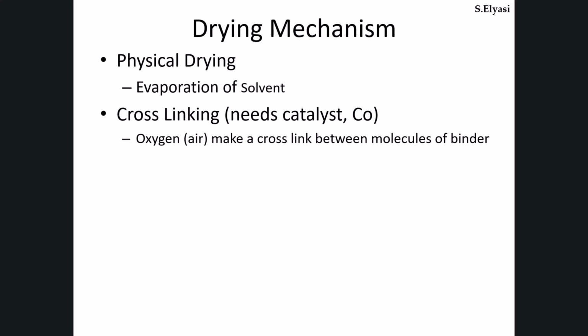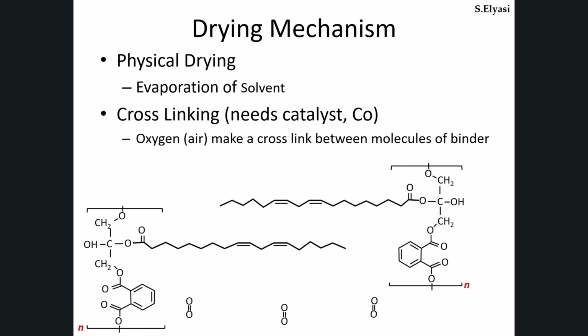Second, the binder film hardens through cross-linking. For many oil-based and alkyd systems, this is oxidative cross-linking. Oxygen from air must first diffuse into the coating film. This diffusion can be slow, especially for thicker coatings. After oxygen reaches the polymer, it reacts at unsaturated sites and forms crosslinks between polymer chains. As crosslinking progresses, the coating becomes harder and more resistant to scratching.